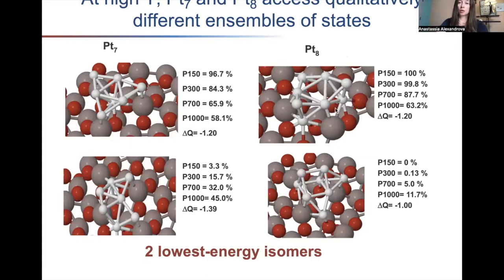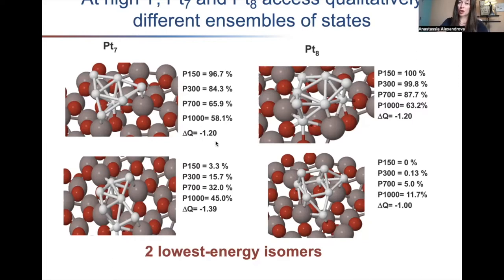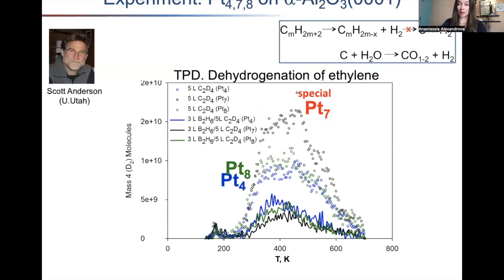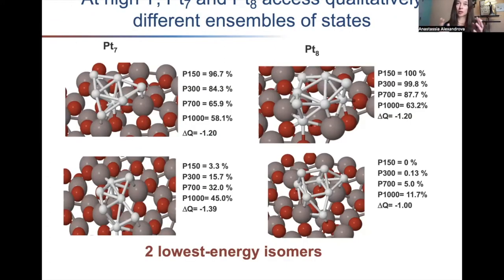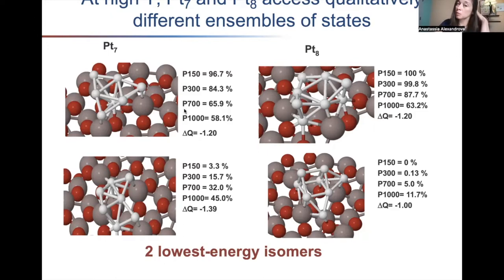The global minimum for Pt7 on alumina and Pt8 show two somewhat globular structures that make some contacts with the support. Delta Q is the charge these clusters draw from the support — they're negatively charged, taking a little more than one electron, and the charge is essentially equal in the two. Nothing really suggests they should have such radically different reactivities at the global minimum level.